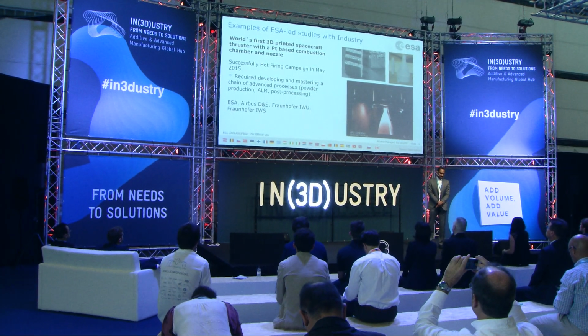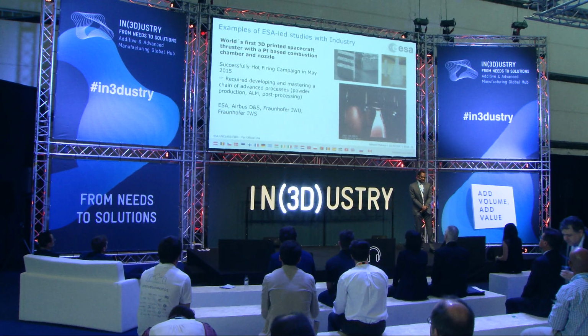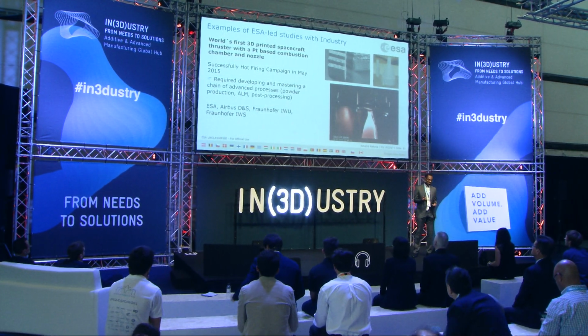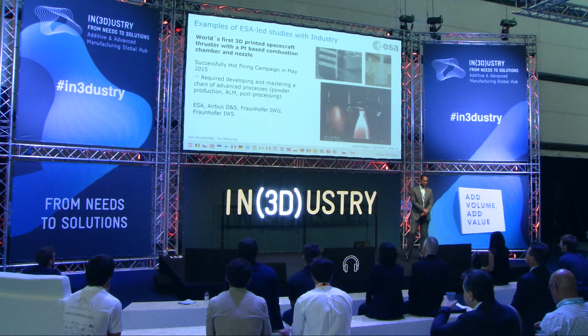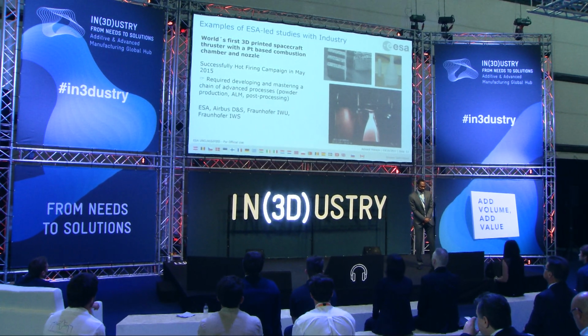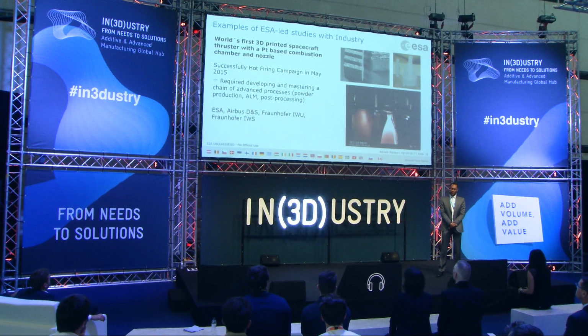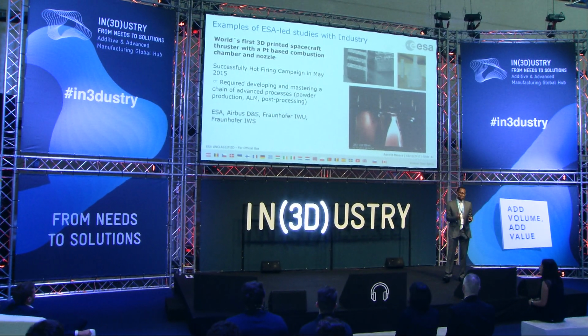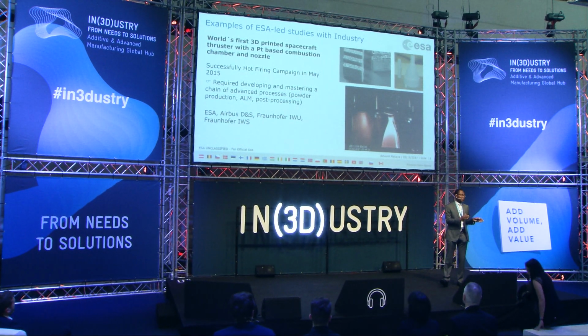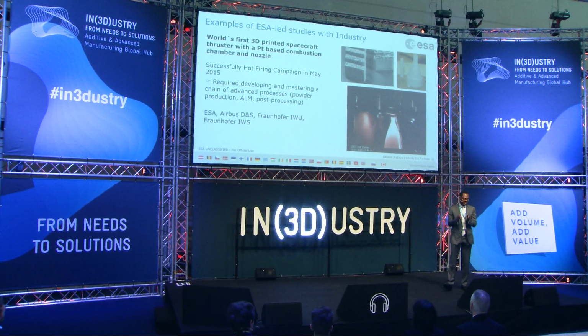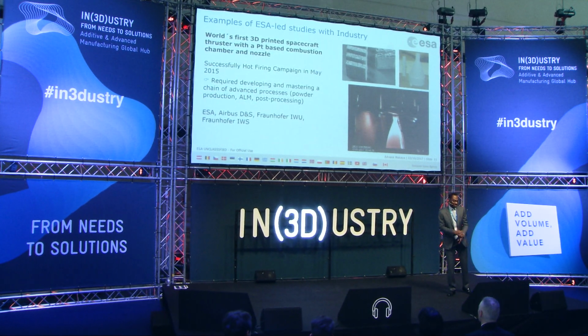This was a very successful campaign performed with our partners Airbus Defence and Space a couple of years ago. We demonstrated the first successful firing of a 3D printed platinum-based thruster. So this was a platinum rhodium alloy, and this first in the world success was actually allowed by mastering different steps of a rather complex chain of processes, from powder manufacturing for these very expensive and rare materials, optimizing the additive manufacturing process parameters, and also the post-processing.